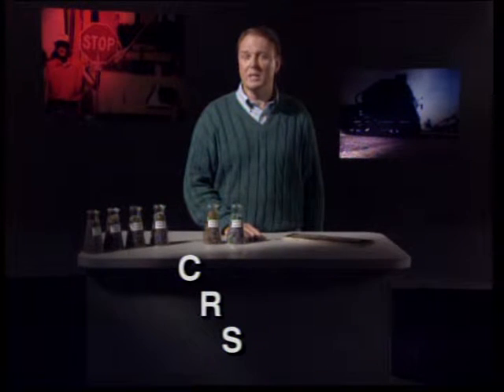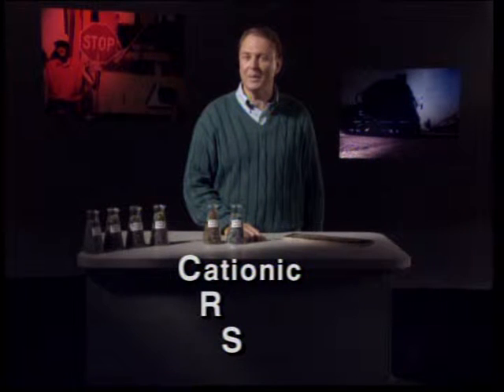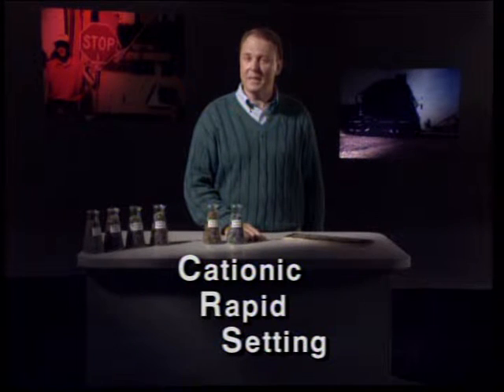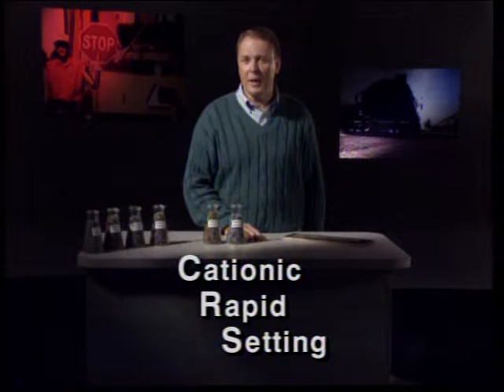For example, one of the most common types of asphalt emulsions is called CRS. The C stands for cationic, which is the technical term for positive. By the way, the term for negative is anionic. The RS stands for rapid setting. The rapid set helps you get traffic back on the road sooner after seal coating. There are also slow and medium setting types for situations where you want the liquid asphalt to sink more deeply into the surface. Besides choosing the types of aggregate and asphalt for seal coating, you have to decide how much